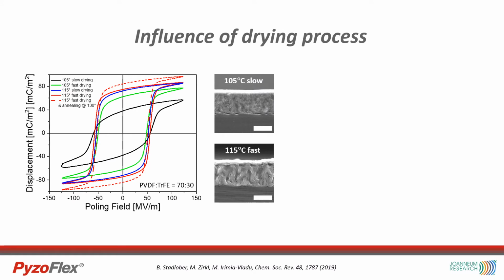The most critical process step is the drying process. Its influence on the hysteresis loop is illustrated on the left. As you can see, when going from the black to the dotted red curve, a faster drying at higher temperatures increases the remanent polarization. We believe that the fast evaporation of the gamma-butyrolactone solvent enhances the growth of crystalline regions in the ferroelectric layer. In the SEM cross-sections on the right, these regions appear as pronounced spherulites. I will come back to that later when talking about ultraflexible devices.